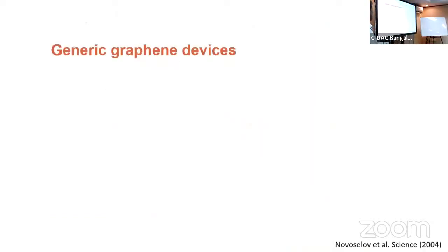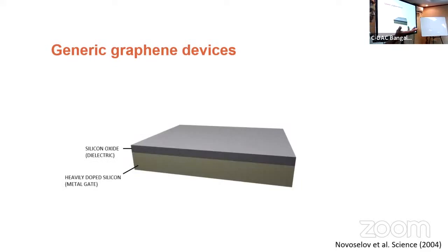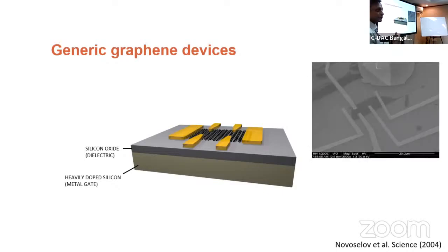Just to give you an idea about how we make these kinds of devices in the laboratory, we take a silicon oxide substrate, and we take a layer of graphene on a scotch tape. This is called mechanical exfoliation. You press the scotch tape on the substrate, and then you remove it, and you're left with a single layer of graphene on top. It's extremely easy, which is why we could do it without the infrastructure. But now, of course, the situation is much better. And then we put electrodes using lithography. That's how a typical device would look when you make it.